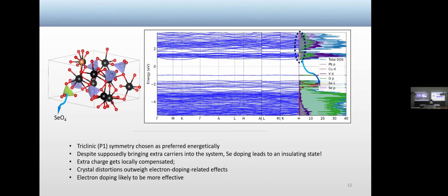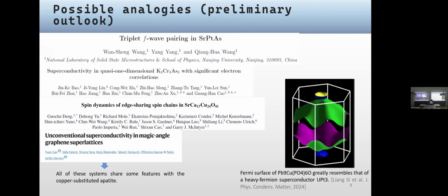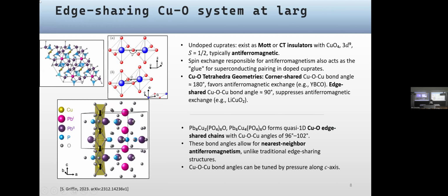Is it copper dominated or copper based? How much copper is it? One per unit cell, but the unit cell is 41 atoms. Meaning that in the non-doped case, it's 10 lead atoms, and in the doped case, one of them was replaced by one copper. So 1 to 9 if we take the metal. In the chemical formula, you showed some case where there is this copper chain somehow. Yeah, it was here.